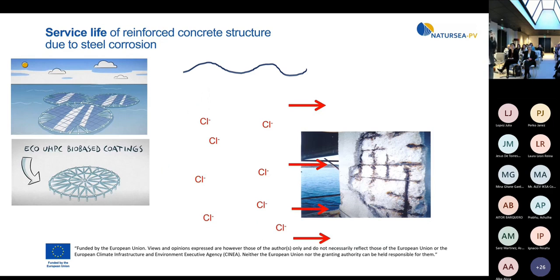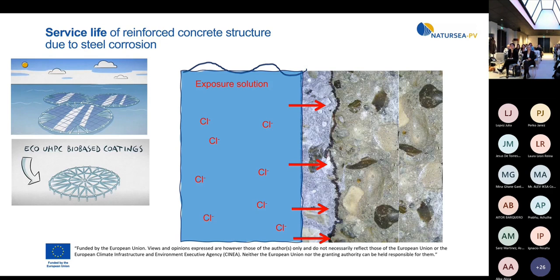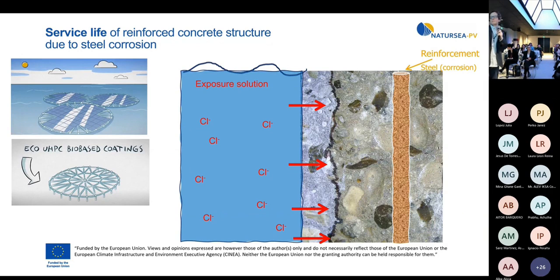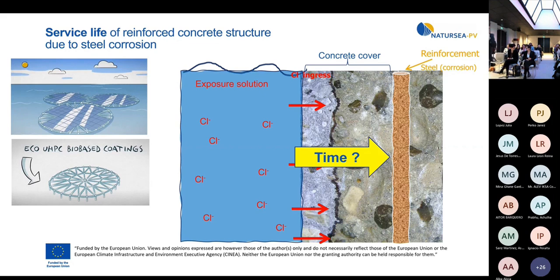So now I will talk about why chloride ingress. This is the cross section and we have a rebar here. The chlorides diffuse or ingress; there are more mechanisms involved. This is the concrete cover, which is responsible for the durability and passivates the steel, because concrete has a high pH. But when the chlorides reach the steel, here you can see the chlorides. If you spray it with silver nitrate, you see nicely the penetration depth. When they reach the steel, they activate the corrosion.